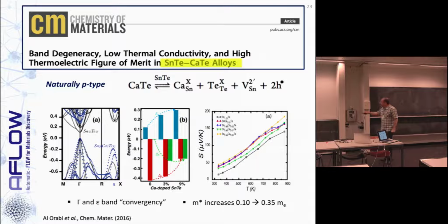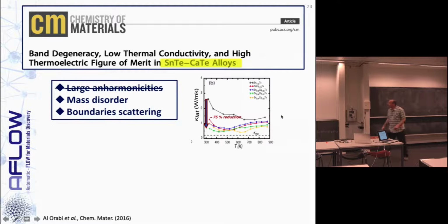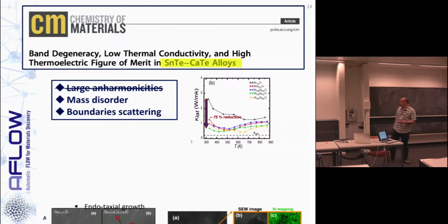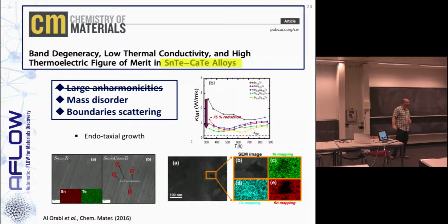So we look at the thermopower. That is another important variable associated with the effective mass, and that increases substantially. Okay? So overall, the material was also good from the point of view of the thermal conductivity. And the reason is that mass disorder, here, the difference in mass between calcium and tin, is sufficient. And in addition, there is boundary scattering forming in an endotaxial way that we would be able to probe experimentally.